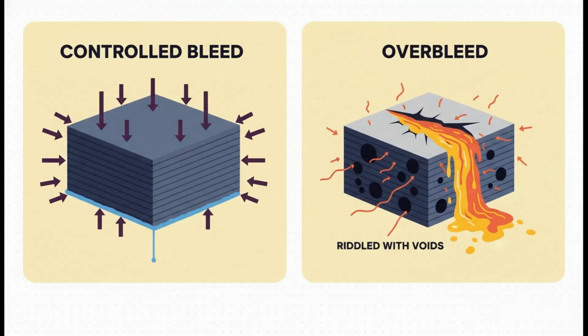And the difference in the final product is just stark. I mean, look at this. On the left, you have a controlled bleed. Just enough excess resin is removed, the pressure stays high, and you get a perfect, strong part. On the right, you have an overbleed, maybe from something as simple as a leaky vacuum bag. The resin pressure crashes, and you end up with a part that's just riddled with voids. It's literally night and day.